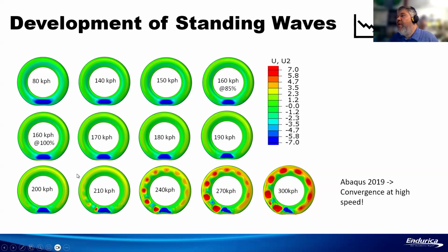However, there's a speed where once you hit a critical speed, the tire starts to develop a standing wave. And this is very damaging to the tire because, below this speed, you have 1 fatigue cycle per rev of the tire. But as soon as you hit this speed, now you have 10 cycles per rev of the tire. And so again, that becomes very damaging.